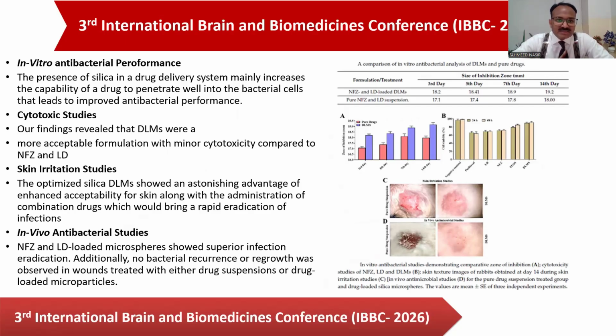In vitro antibacterial performance was done by performing the zone of inhibition test, and it confirmed very good antibacterial performance. Cytotoxic studies were performed and confirmed that the formulation is acceptable, because it showed very minor cytotoxicity. Skin irritation studies confirmed very minor skin irritation and rapid eradication of infection. And in vivo antibacterial studies confirmed that no bacterial reoccurrence or regrowth was observed. So it is very good for wound healing, for superficial wound healing.